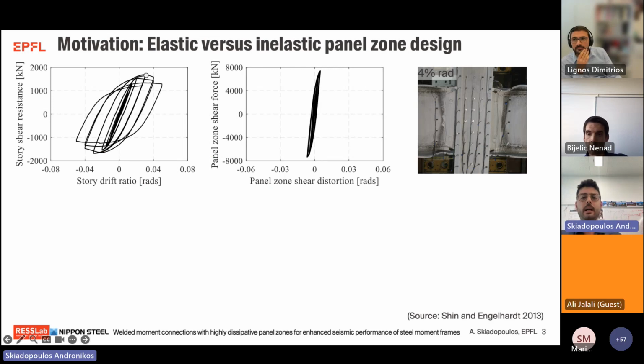Here we see a typical beam-to-column connection test of a welded moment connection, where in the left figure we see the global response of the beam-to-column connection. On the right side we see the panel zone response. And what we observe here is that at 4% story drift ratio, the connection loses more than 20% of its load carrying capacity. And this is because beam local buckling initiated at 3 to 4% story drift ratio, as shown in the far right figure.